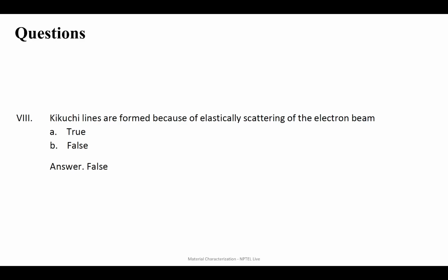So the answer to this is false. For Kikuchi lines, first there has to be inelastic scattering of electrons, which are then elastically scattered according to Bragg's conditions.